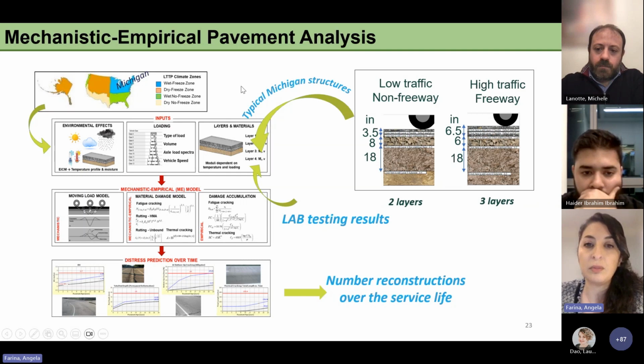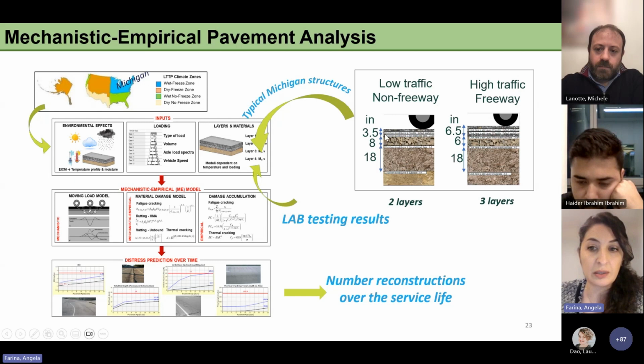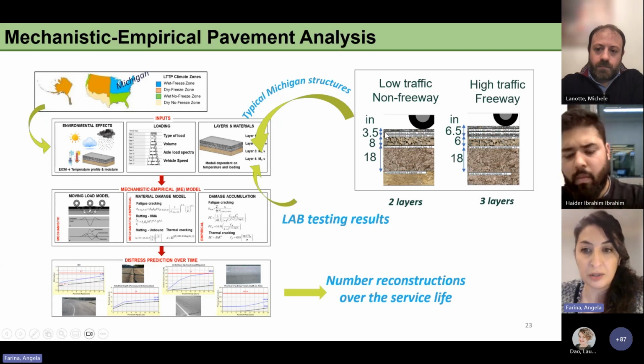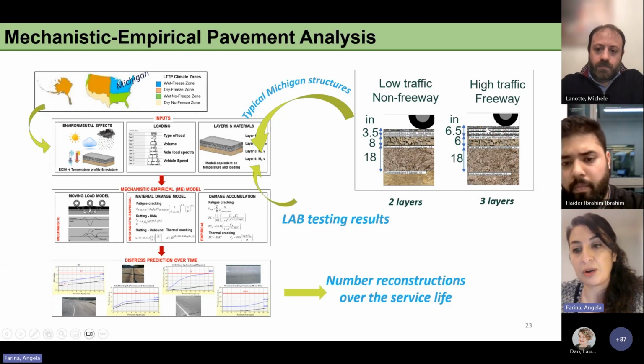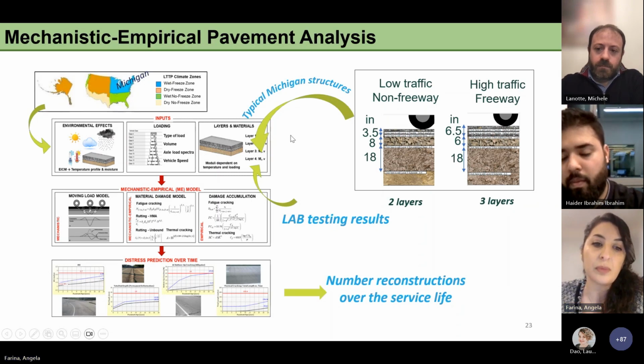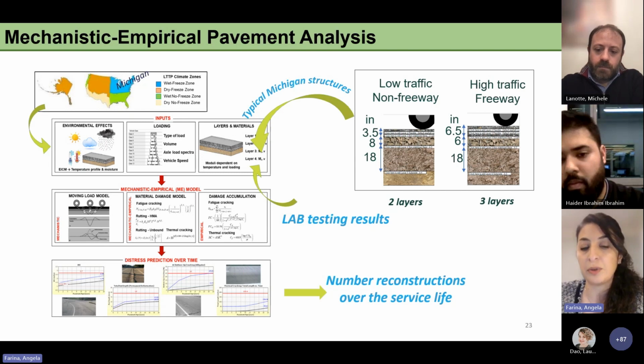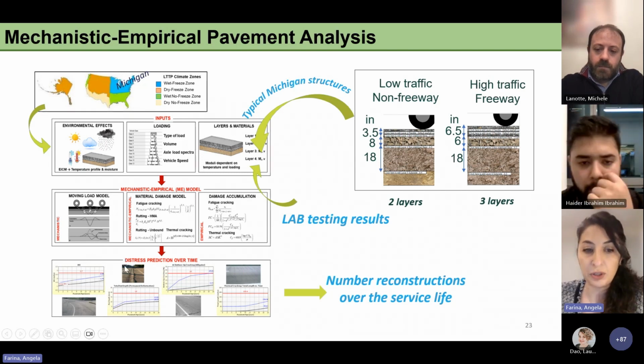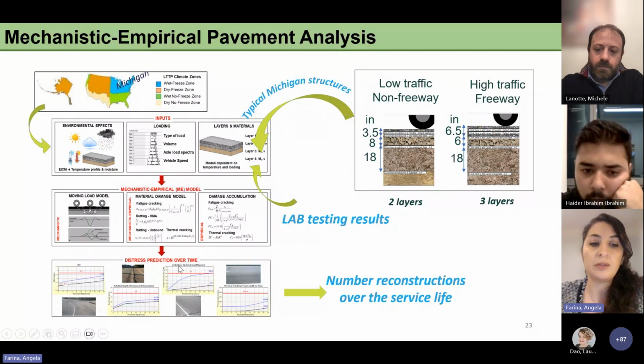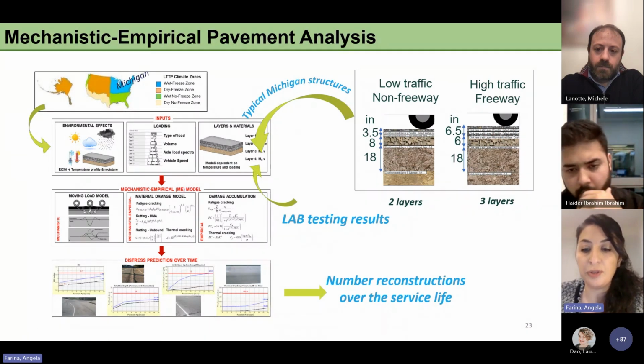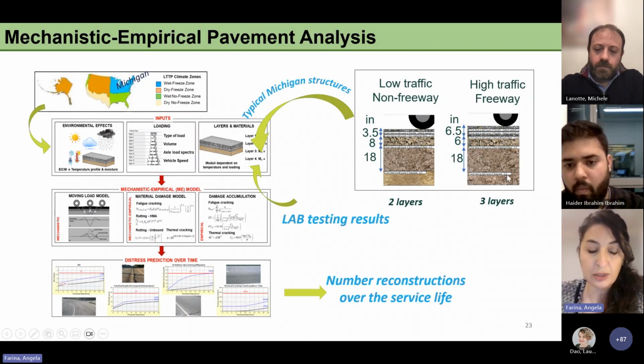And I consider two typical structures in Michigan, one for the low traffic level and one for the high traffic level, where we have here the two layers of HMA as a surface layer, and here for the high traffic, three layers. So then the software calculates the material damage and the damage accumulation, the distress prediction over time. And based on this, I calculated the number of the reconstruction over the service life for these two pavement structures.